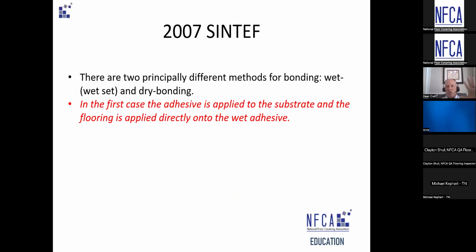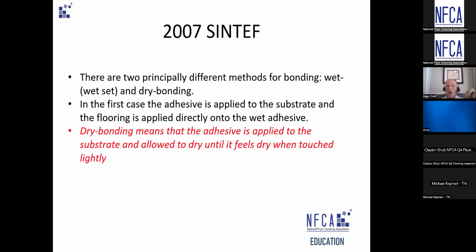And SINTEF goes into wet and dry bonding. I only go through this not to tell you guys how to install flooring, but to show you how far back the idea of how important the substrate surface absorptivity is. Even 17 years ago, they talk about the substrate and what kind of bonding technique should be used. If it's a wet set adhesive, where is that additional liquid going? You only allow it to off-gas so much, or you lay the flooring into the wet adhesive. It'll either cure on its own or be absorbed. Is that adhesive's pH tolerance high enough to survive in that environment?